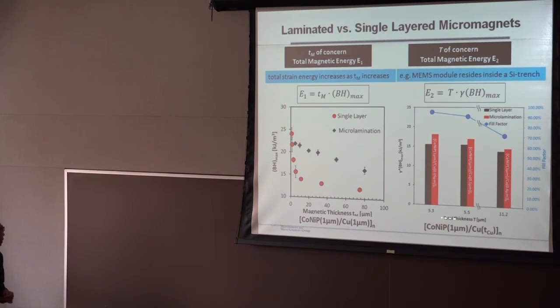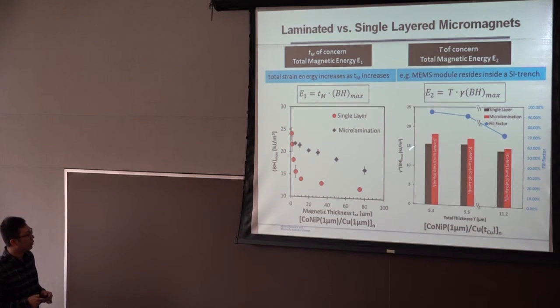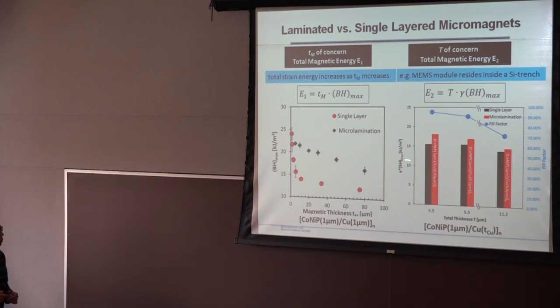Here we show a plot comparing the fill factor modified BH max versus the total thickness. And here are some possible designs where you can utilize the opposing effect of the fill factor to achieve, with the same total thickness, a laminated structure that can still have a larger total magnetic energy compared to the single layer.